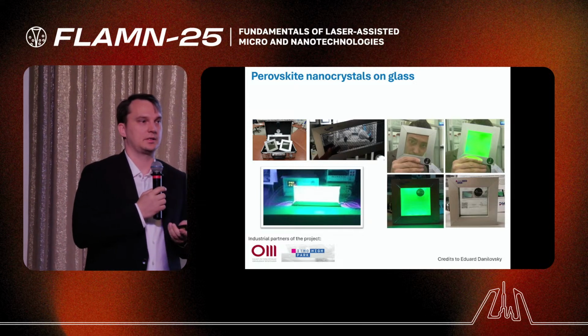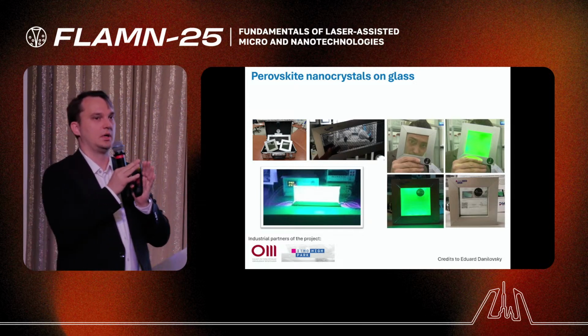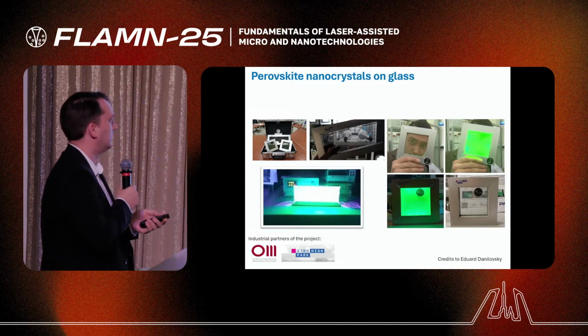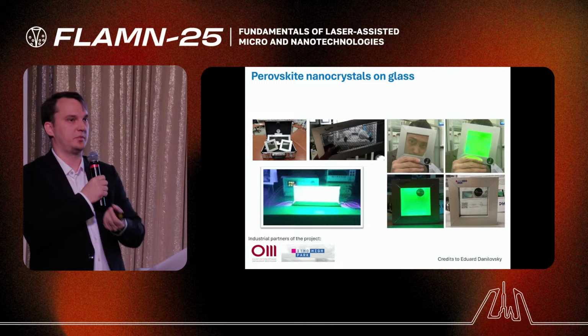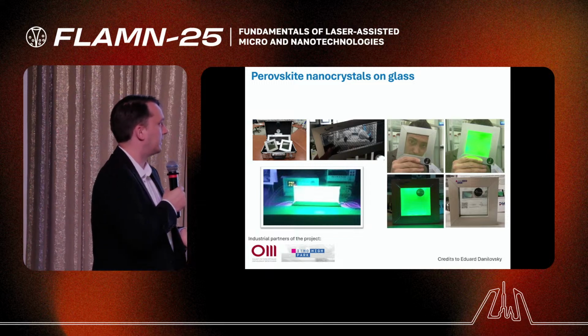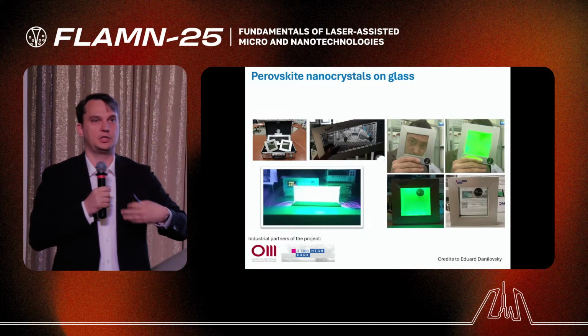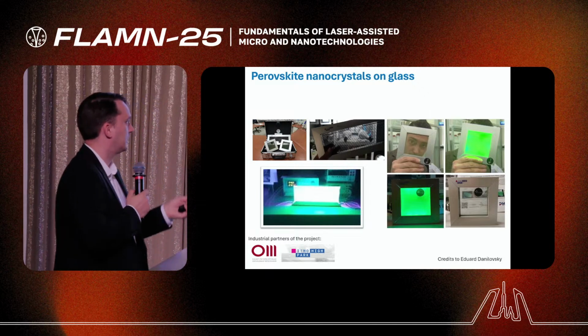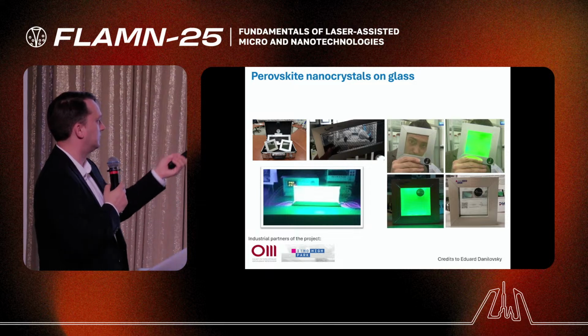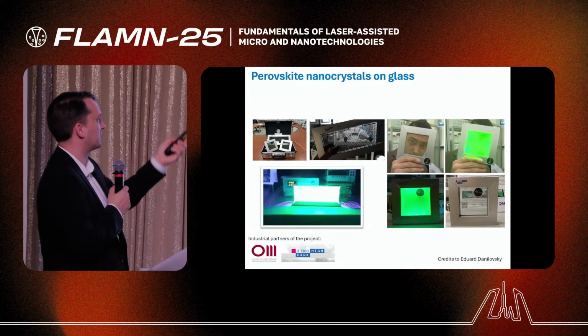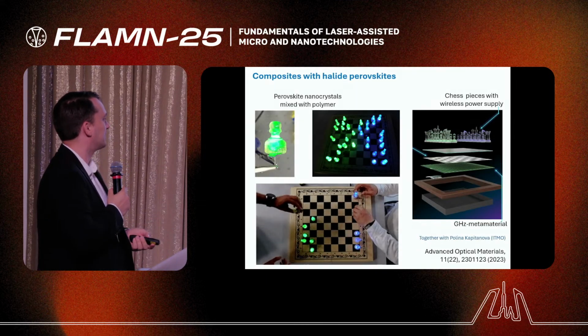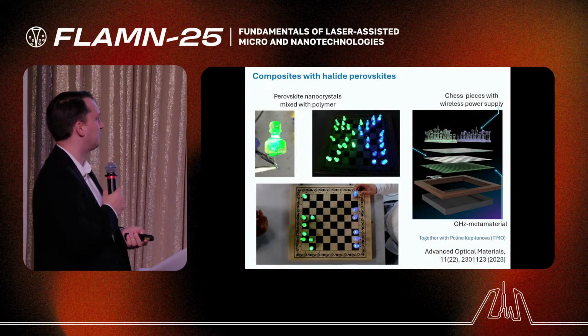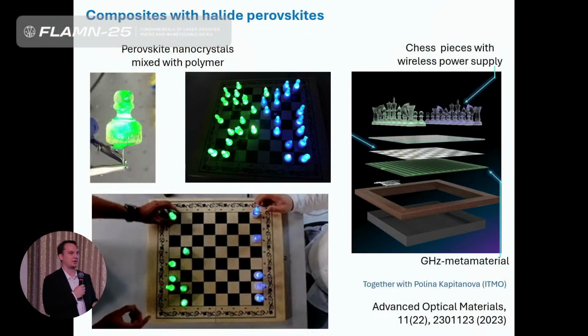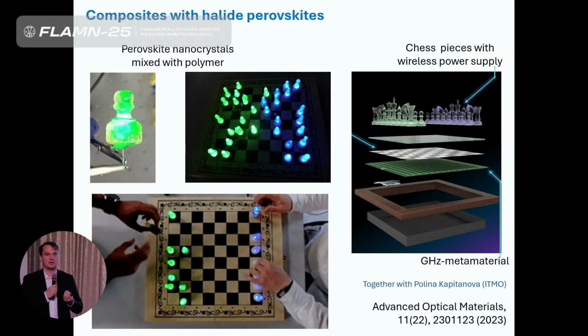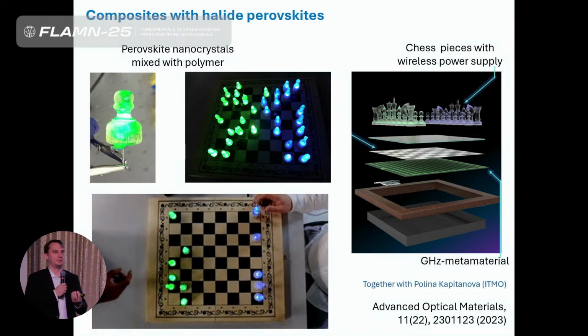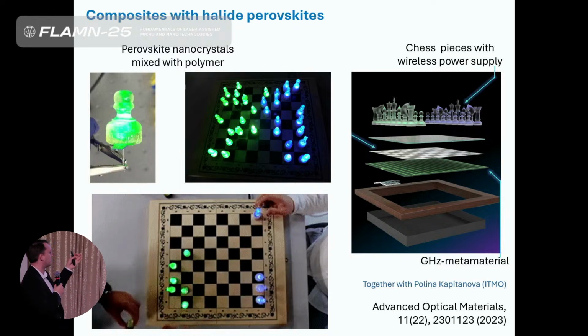So here you also see that when we deposit halide perovskite between two glasses, then we can excite them by LEDs in this frame, and the emission is really very bright. You see that it can even block the face of this LED. And there are also some examples of incorporation of halide perovskite nanocrystals inside polymer-based objects, like chess pieces. In these cases, they can be of arbitrary shape.